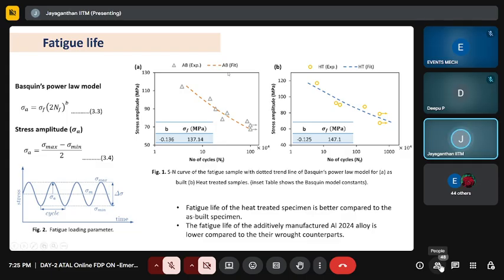Basically we are quantifying high cycle fatigue, and on the extreme right side we also show the heat treated sample. The fatigue life of the heat treated sample is better compared to the as-built sample. Yes, due to microstructural refinement or transformation, we are trying to show this in the extreme right side picture. Heat treated sample provided better fatigue properties. And again, see stress versus number of cycles to failure. Look at the loading pattern.